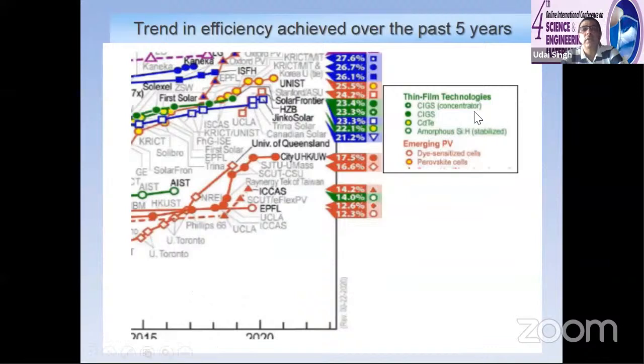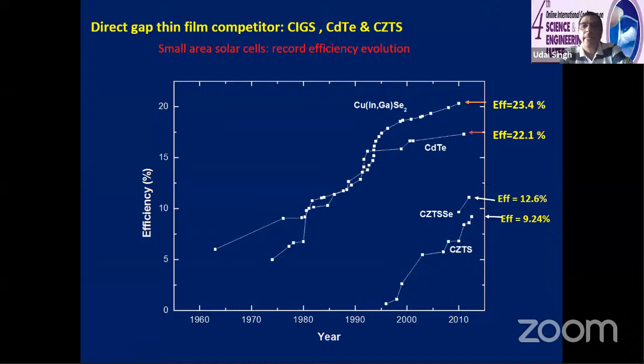If you see thin films like CIGS, this 23.4 is the highest. Then I will be talking about the CZTSSe, where 12.6 is the highest efficiency achieved. Cadmium telluride reached 22.1. These are all lab efficiencies: CIGS 23.4, copper zinc tin sulfide 9.24, and copper zinc tin sulfur selenide 12.6. A lot of work has to be done, because for more than 3 to 4 years, efficiency has not increased for these kesterite materials.